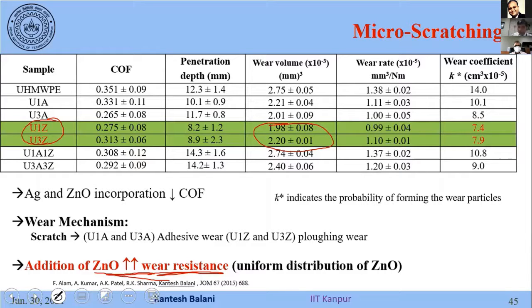So in fretting, zinc oxide was actually harmful, but here I am observing that zinc oxide is helping, lowering the wear volume or increasing the wear resistance. That is very strange. How can one entity increase as well as decrease somewhere else? Because this is a different methodology. In fretting, we are giving some sort of frequency or vibration. Even if the zinc oxide, which is a rod, moves from its surface, it creates a gap in between, and that gap is taken as wear volume. But it is not gone out completely. Zinc oxide is much harder than polymer. So once I go to a higher length scale, I realize the real potential of it. It is actually helping, not deteriorating.